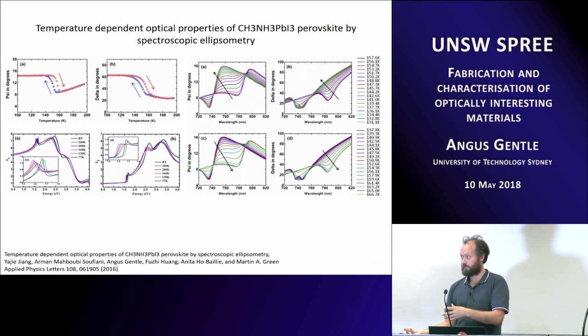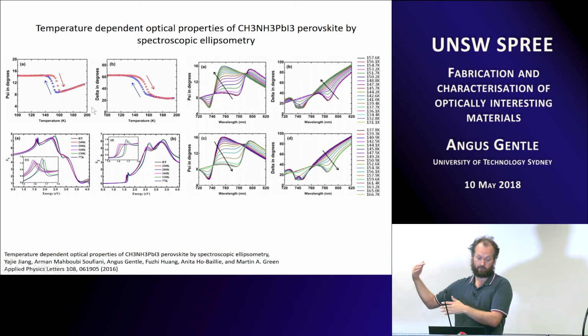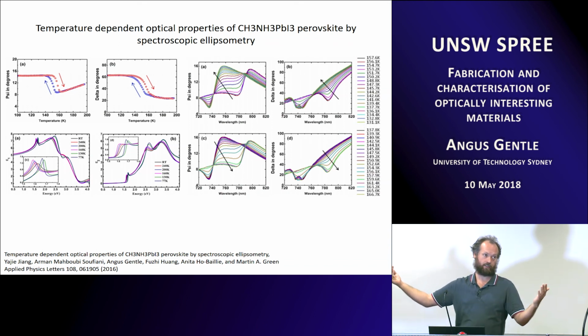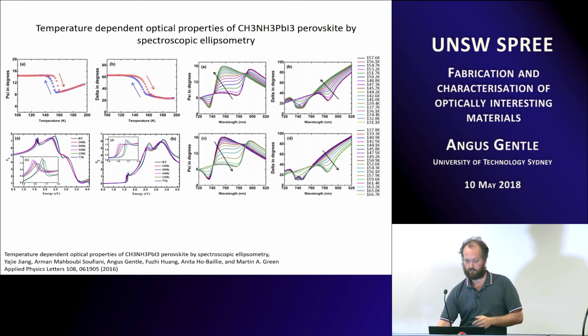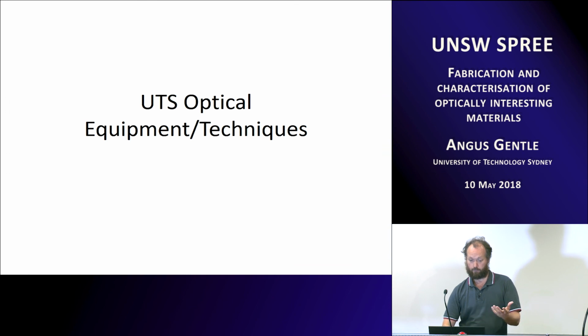So we do temperature dependent ellipsometry as well. Cool. So this was basically looking through and scanning through on a perovskite, going from room temperature down to liquid nitrogen temperature. First of all, did some scans across the whole range and then narrowed down. So this is over quite a narrow temperature range and measuring it as it goes through the transition. Other equipment we have down there.